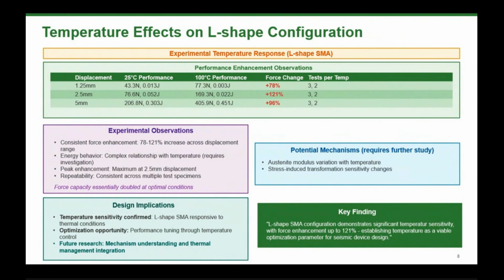And then we moved to a comparison on temperature, and we made it on the first configuration that demonstrated to be the most balanced of the three. And we found that this joint, as we know, is very, very sensitive to temperature, because we found a force enhancement up to 121% with temperature. So temperature is a parameter to take into account and to optimize for the next design of the final seismic device.